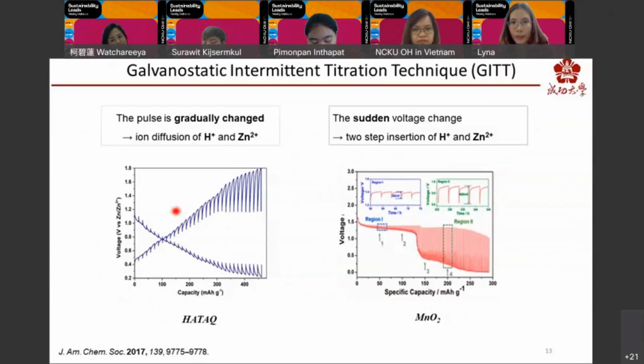The mechanistic study of HATAQ was further carried out using GITT and EIS. In GITT, the pulse signal gradually changes during the discharge process, which can be attributed to ion diffusion of proton and zinc ion. Our result is different from the previous report shown in this figure, where a certain voltage change indicated the two-step insertion of proton and zinc ion into the manganese oxide material.